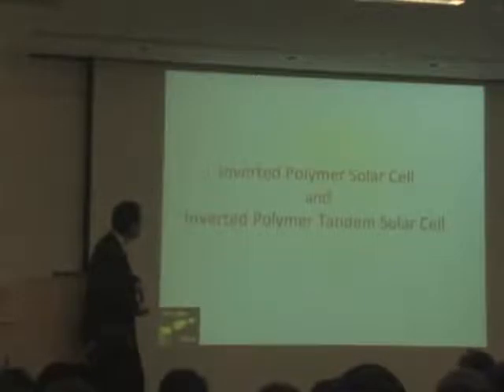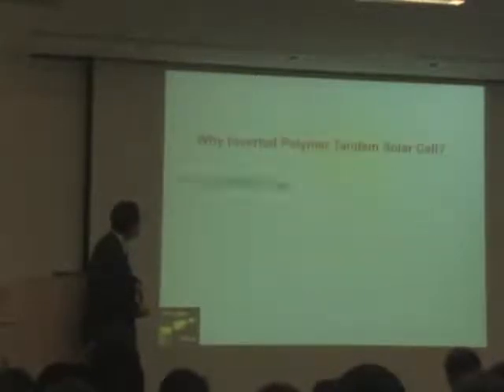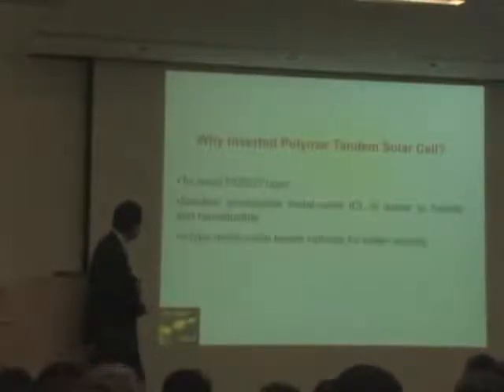So why do we do inverted? We can avoid the PEDOT potentially, but we still use them. Solution process, the metal oxide interconnecting layer is easier to handle and reproducible. And the metal oxide is based on the cathode for better stability. So we don't have to use calcium. You probably noticed some of my devices using calcium, which is not the most reliable material you want to use. So let me give you an example.